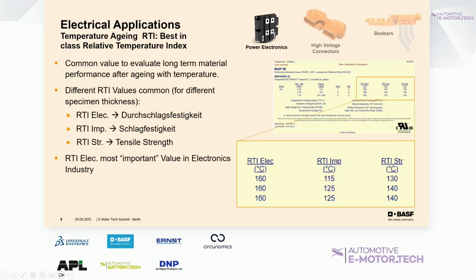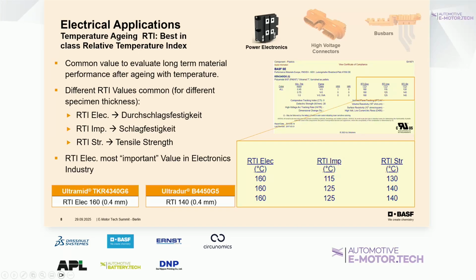Additionally, we see much more demand also for so-called RTI listings. Especially if you talk about power electronics, it's a value that is often required, the so-called relative temperature index. It's a value which describes mainly the material performance after aging with temperature. Here you have the yellow card, a typical yellow card provided by UL. You have these different listings for RTI electric, so the RTI strength and also the impact strength. What we see as a trend is that especially RTI electric values are much more requested at the moment compared to a few years ago for power electronics, and the values are also getting higher. In the past we talked about 140 degrees that a material typically needed to withstand. Now we see more 150, 160 degrees, and in some special cases up to 180 degrees.